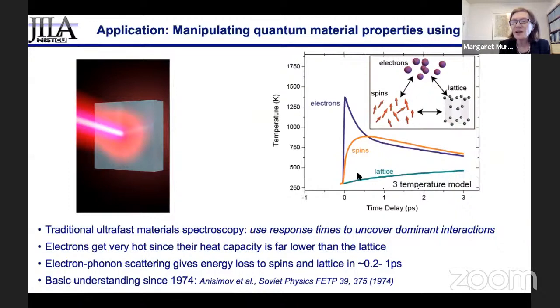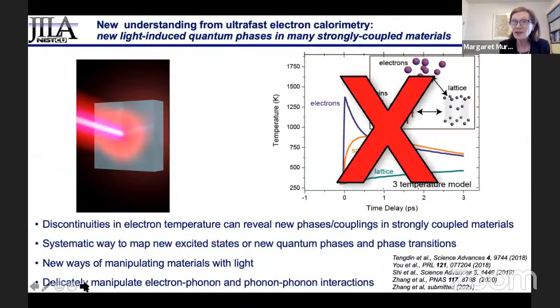If one is looking at a system with strong interactions, then if the material undergoes a phase change while the electrons are cooling, then you should see that phase change written onto the electron temperature. And actually you can see that. So now we know that this is not a good interpretation for magnetic systems, for charge density wave systems, anything with very strong interactions.